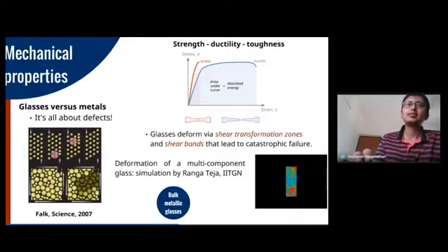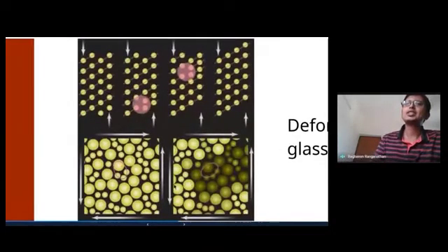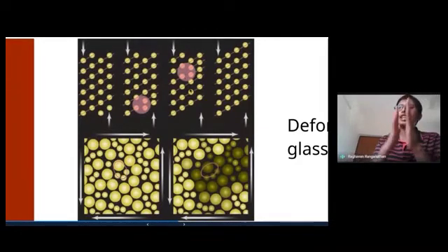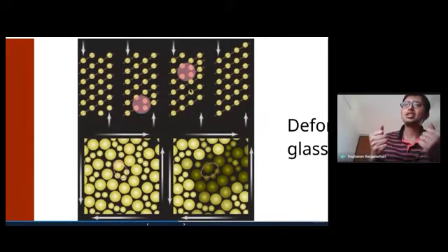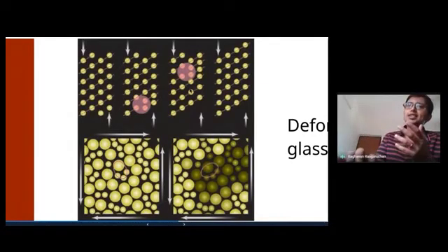Whereas metals are ductile. And the reason for that is the makeup in terms of the structure. So what we show on the top are atomic planes of a metal or a crystal, and crystals basically deform by what's called a dislocation mechanism. So there are planes of atoms that can slide past each other, and that allows the material to withstand a much larger load in the plastic regime. This material can be pulled for much larger strains than glasses. So glasses, as we see in the bottom set of figures, form what's called a shear transformation zone.